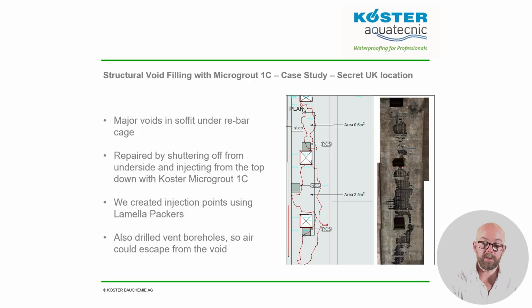The picture to the right is the underside of a concrete deck after the shutters were struck. There were very large voids within the concrete. The rebar was packed very tight, and it seems like the aggregate in the concrete just never made it through to the bottom. To tackle this, the underside of the slab was shuttered off and sealed around the edge. From the top, 18mm boreholes were drilled, Lamella Packers inserted. A number of vent holes were also required, so when the microgrout was injected, the air within the void could easily escape. When the injection was finished, the microgrout could be seen flowing out of the vent holes, proving that the whole void was filled.